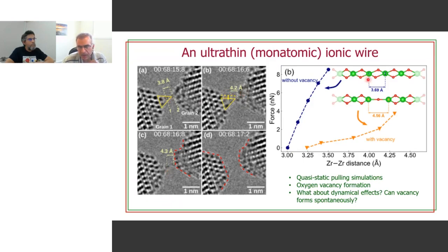This is impossible for a stoichiometric wire. If you try to extend this wire, it breaks much before reaching this distance of 4.3 angstroms between two neighboring zirconium atoms. So the only way this is compatible with theory, and these are DFT calculations, is that you have to conjecture that there's a formation of an oxygen vacancy in this process. If there is an oxygen missing here, then you can go to larger distances, even 4.5, 4.6 angstroms. So these are results of quasi-static pulling simulations using DFT that point out that there is a formation of oxygen vacancies leading to the process of monatomic wire formation in this system.